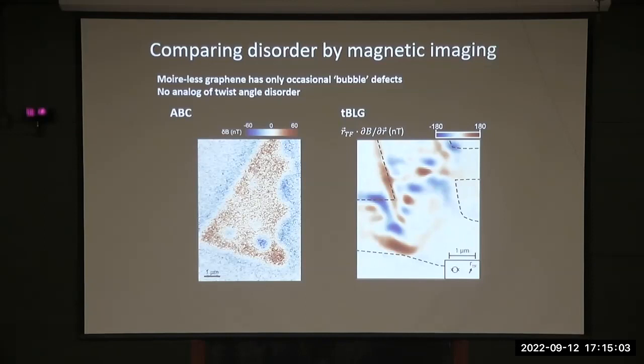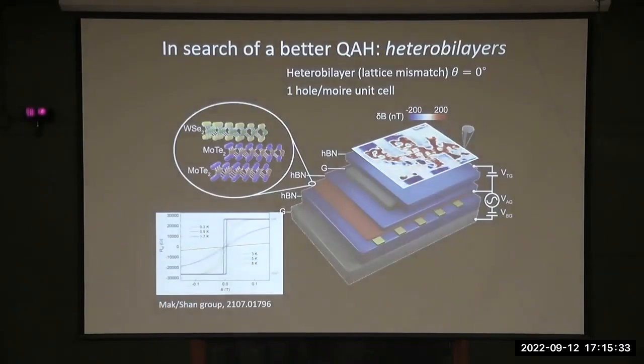The reason for that is that twisted bilayer graphene is at magic angle, it's magic for the electronic structure, but it's not magic for the structure. It's not even a metastable state, it's simply unstable. So you're quenching in whatever disorder there is when you make it, and it's just very hard to do that in a way that's perfect. You can't rely on any kinetics to help you. They're just your enemy, right? And so generically you get very disordered magnetic structure, and you can do many other types of imaging and see that it's just all over the place most of the time.